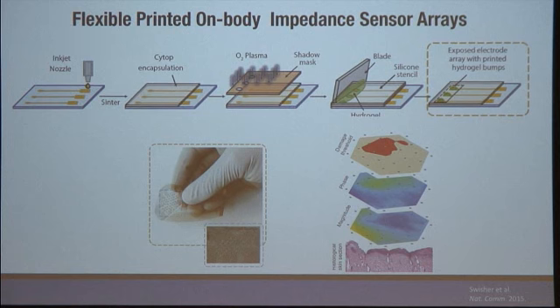of the areas you don't want it, and only wet the areas that have been made hydrophilic by this oxygen plasma step, atmospheric step, not a vacuum step. And then you build up and actually can print additional hydrogel bumps onto this process. Sorry, the hydrogel is the wetting process, produces hydrogel bumps. This can be used, this is an impedance sensor array. So this is an array of hydrogel sensors, and you're doing impedance measurements for wound characterization.